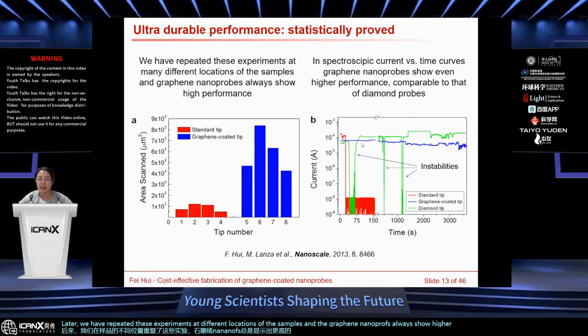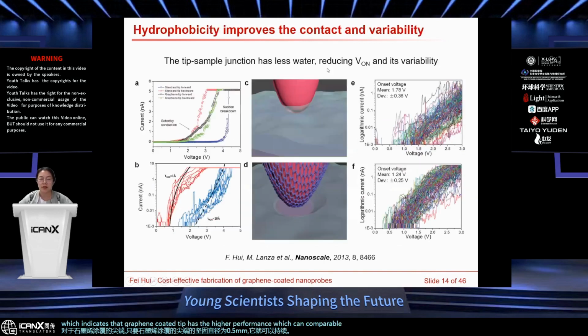performance. In addition, in the specific IT curves, we have found that for the standard C-AFM tip, at high current density, it only lasts a very short time. And the graphene-coated tip can last as long as the robust diamond tip, which indicates that the graphene-coated tip has higher performance, comparable to diamond probes.